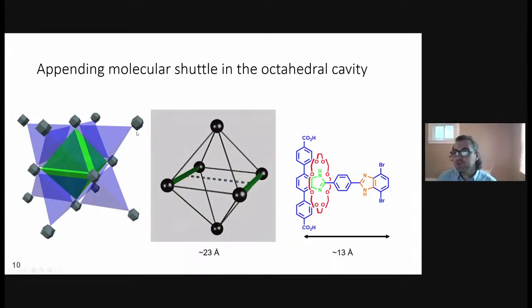So obviously, if the tetrahedral cavities are too sterically confined, the obvious solution is to simply put the rotaxane in the octahedral cavity, which is larger. So this, in terms of the cross-linking approach, is quite challenging because it's quite a long distance across this octahedral cavity of about 23 angstroms. And this means that simply designing one of these H-shape type linkers that can cross-link this is not that straightforward, as there's not a nice even number of phenyl rings that we can simply make into the axle that will stretch across this cavity here.